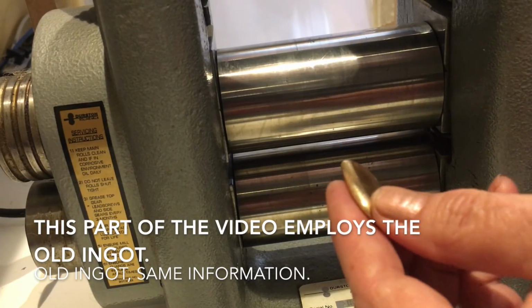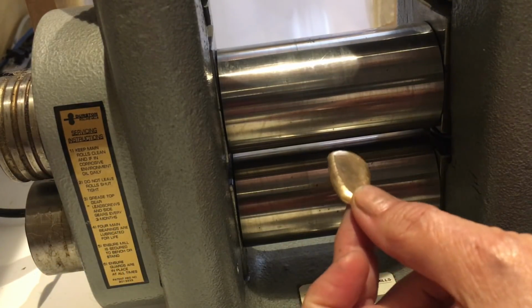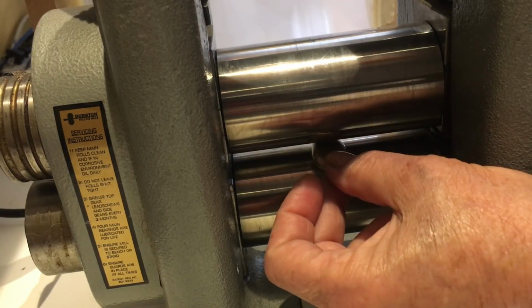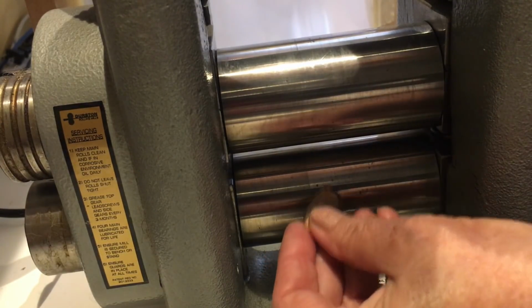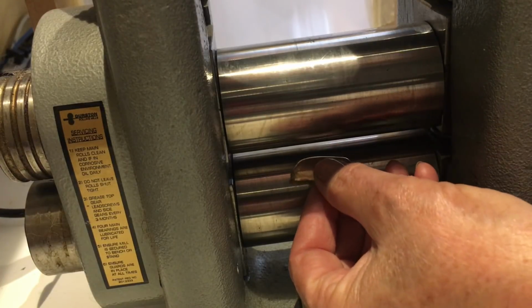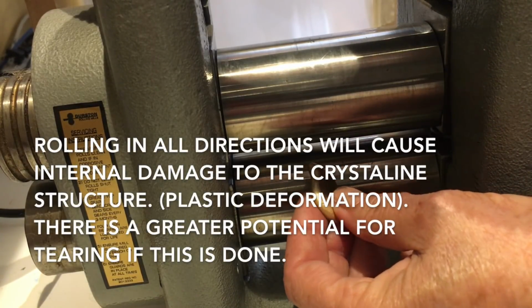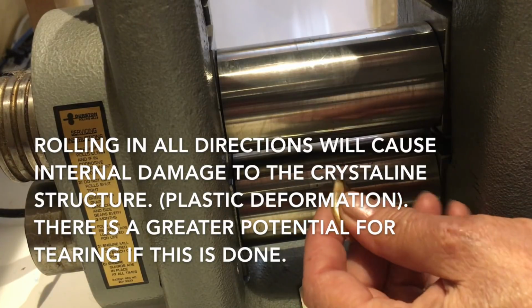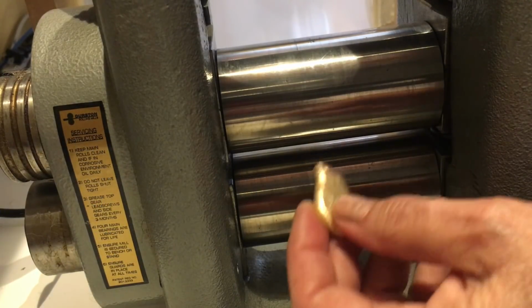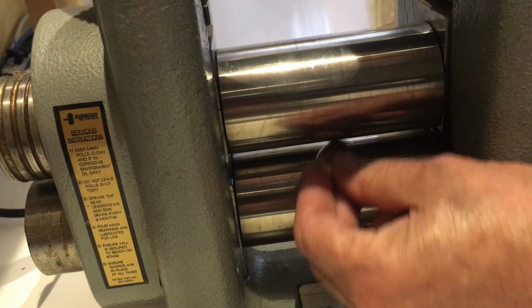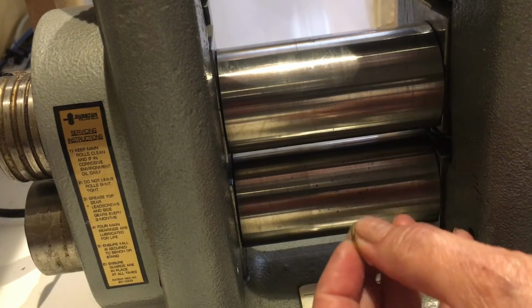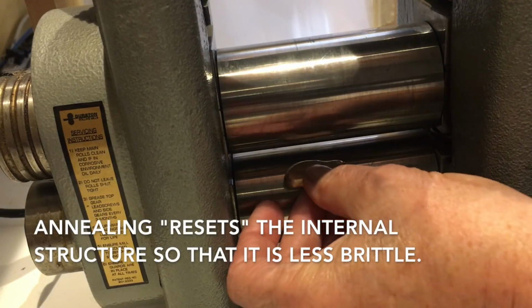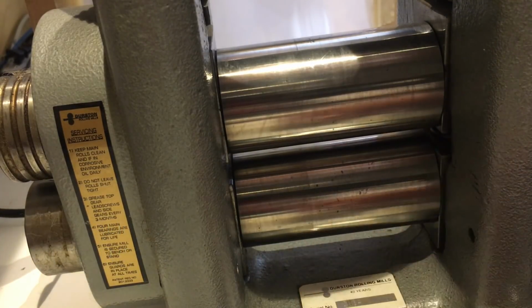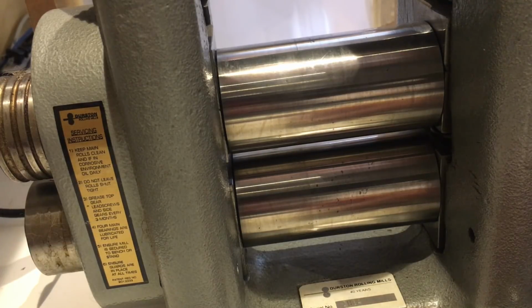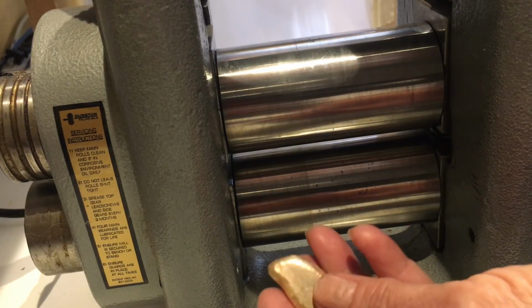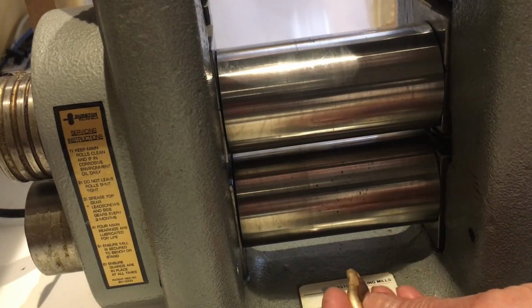What you want to do is keep the rolling in the same direction. So if I'm going to go longwise in here, I can put it in this way, or I can flip it around and put it in this way. That doesn't matter. But what I can't do is go crosswise. It will cause some cracking and other issues down the road. That's in between annealing. So I'm going to roll it through going this way, and then I'm going to anneal it, and then I'm going to roll it through going this way, tightening the rollers down each time.